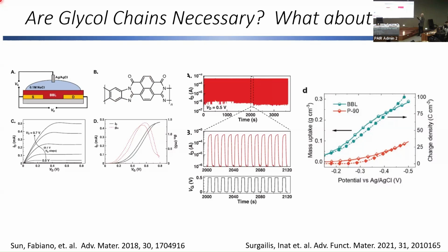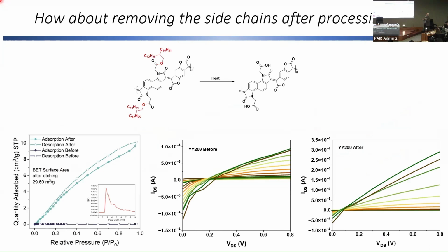But when you do that and you drive it off, you can get, in this case, a very high volumetric capacitance because there's no inert component. All the polar ions can be easily compensated by the polymer. So here we see that the mass uptake of our ions is much higher for BBL than it is for one of the polymers that I showed you earlier, forward and reverse. So these polymers have a much higher volumetric capacitance because they can be charged at higher density. So very new stuff. We haven't published any of this yet, but this is just one thing that we're doing now as well. Can we mimic this and get the best of both worlds?